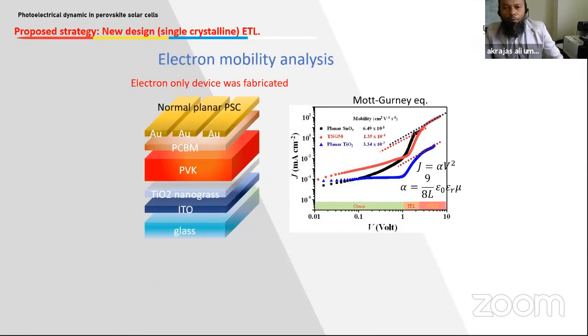Now, to further examine the nature of the photoelectrical dynamic in this new system, we carry out electron mobility analysis in the device by fabricating an electron-only device with the structure of nanograss and PCBM. Both of these materials are electron transport materials, and we record the JV curve, and then we fit the result using the Mott-Gurney equation. Then we got the space charge limited current electron mobility in nanograss, which is very much higher compared to SnO2 based devices, and even most TiO2 based devices. So this is one of the strong pieces of evidence that the new design of ETL is very useful for the improvement of photoelectrical dynamic in the devices.